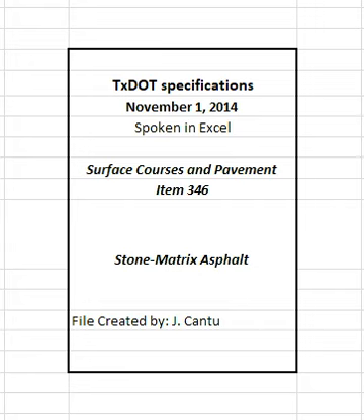4.7.2 Tack coat. Clean the surface before placing the tack coat. The engineer will set the rate between 0.04 and 0.10 gallons of residual asphalt per square yard of surface area. Apply a uniform tack coat at the specified rate unless otherwise directed. Apply the tack coat in a uniform manner to avoid streaks and other irregular patterns.